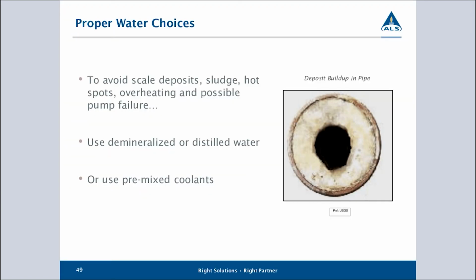Again, this is an example of what tends to happen in the pipework. To get the level that we're seeing in this picture, we would need something like almost river water being used in the system as opposed to tap water. But where you've got a high degree of dissolved salts in the water, it will plate this material out inside the cooling system.